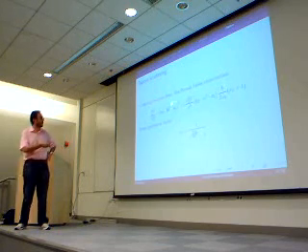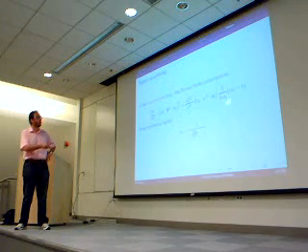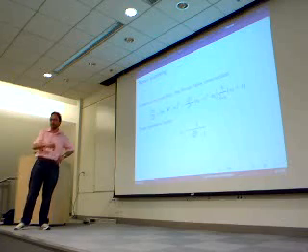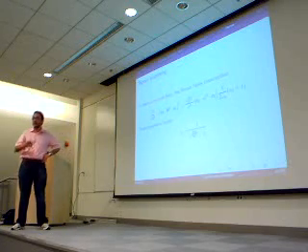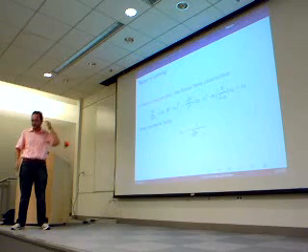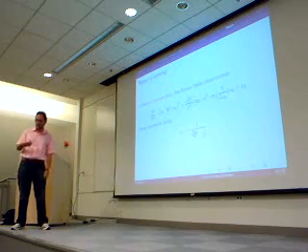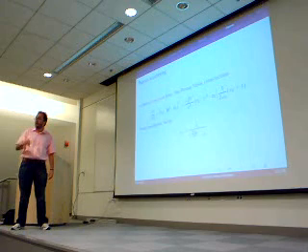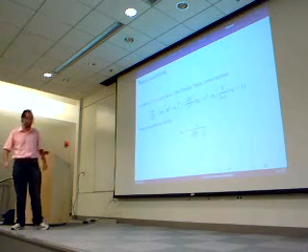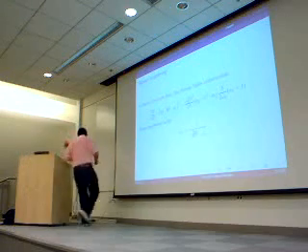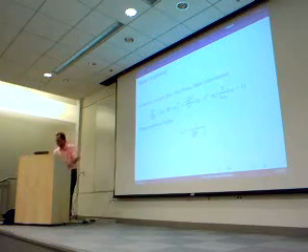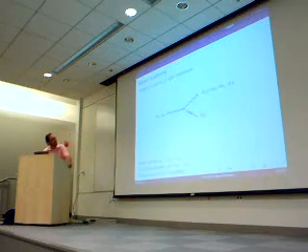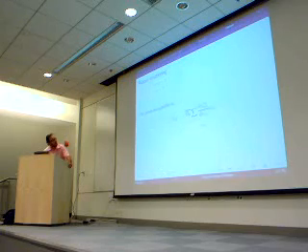So in the formula for the anti-Stokes process, you don't have this factor of plus one, and this factor is quite small. So the Stokes process, in which phonons are created, gives origin to Raman lines which are much higher than for anti-Stokes processes. So usually Stokes is measured.